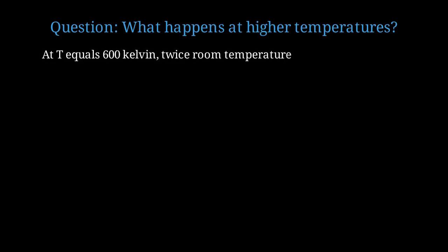Suppose we heat to 600 Kelvin, twice room temperature. Now EB over kB T becomes approximately 19.3, and the relaxation time becomes approximately 0.2 seconds. Notice the dramatic change: just doubling the temperature reduced the relaxation time from 1 day to a fraction of a second. This demonstrates the exponential sensitivity of the relaxation time to temperature. This is key to understanding the paradox.